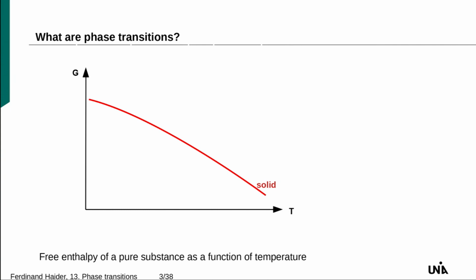The first thing I already introduced in one of the other lectures: if we consider free energy as a function of temperature, dG/dT or dF/dT is minus the entropy, so it's a falling function with temperature. It typically looks like this with a slight curvature, but the temperature dependence of the internal energy is not very large, so we can approximate it as a straight line. This is one phase. If we have another competing phase, for example a liquid, the liquid has a higher entropy, so a steeper slope, and at some point there's an intersection - that's what we call the phase transition temperature, because in equilibrium the free enthalpy is minimized.